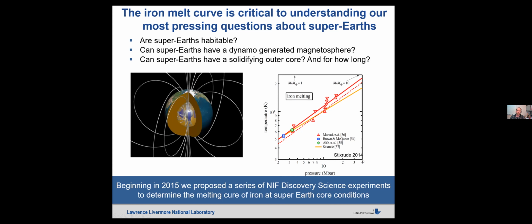or 4,000 gigapascals. And so what you're looking at over the range of course, one Earth mass, the center of the Earth is at 365 GPa, and 10 Earth masses are up here at around 3,000 GPa. The only data point really on this plot at this time was shockwave work, up at there 250, 260 GPa. Everything else is calculations. And of course, calculations are getting better and better, but we'd really like some ground truth information on the melting curve of iron to best start addressing these questions.